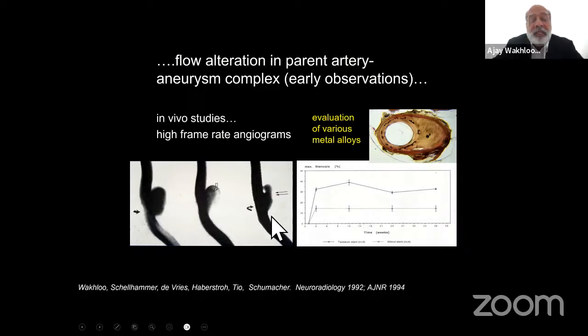And then first we thought it is an interaction between the alloy and the blood components. So we used a different material. You see, this is tantalum, and down there is nickel titanium. And we studied these animals for 6 months, and there was a difference as far as the intimal buildup is concerned. We had more reaction with tantalum, which we then later didn't use, as you know, but nickel titanium basically prevailed as a good material.